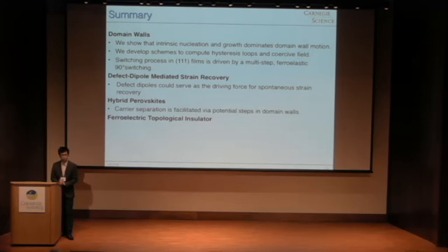You see, if you have films with thickness very near to the critical size of the domain, the size of the critical nucleus of the domain, there is no space for the domain process. You can have nucleation, you can have the initial stage of growth, but you cannot have such a process as was investigated by Kolmogorov, Avrami, Ishibashi. You understand me?